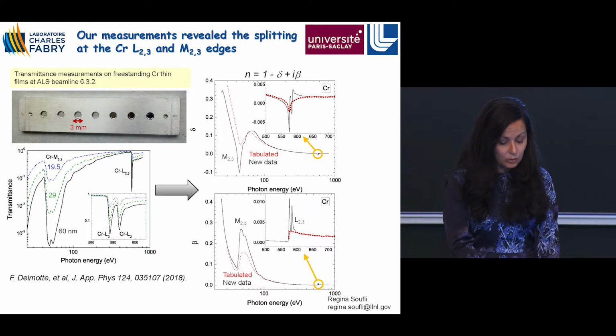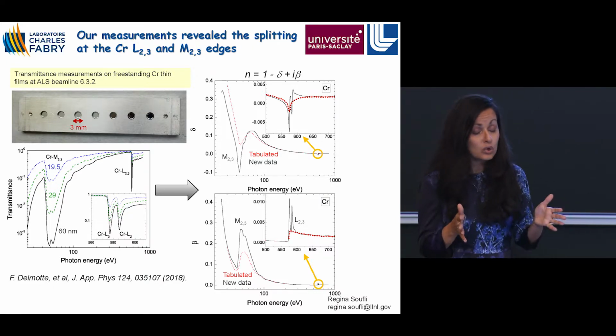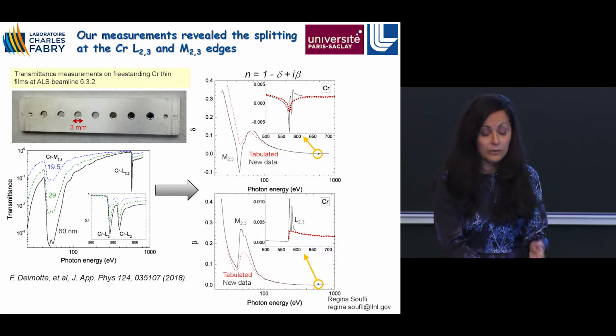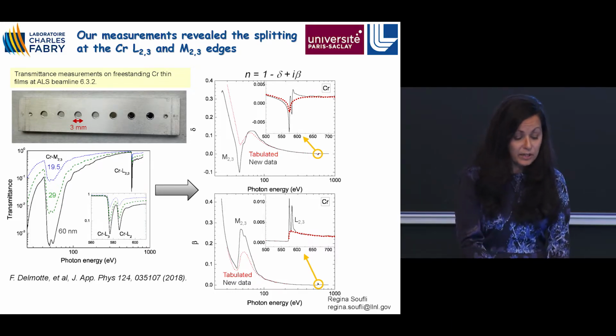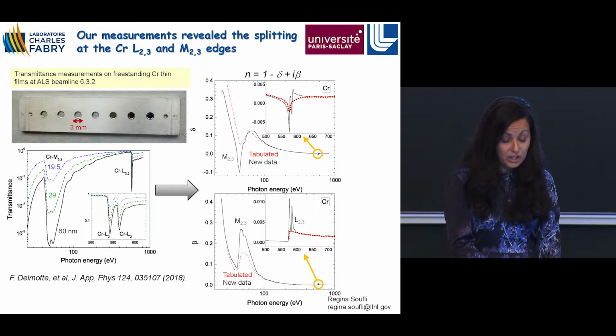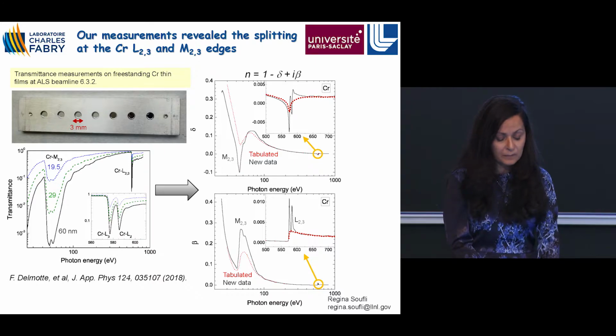And then we had to do measurements in an extended photon energy range that starts at about 20 eV and goes to about 1 keV. This means we had to change lots of settings at the beamline for those of you who are familiar with the synchrotrons. And I hope you can appreciate the nice continuity of the data that we got, the overlap. I'm showing here 3 out of the 6 films that were measured.